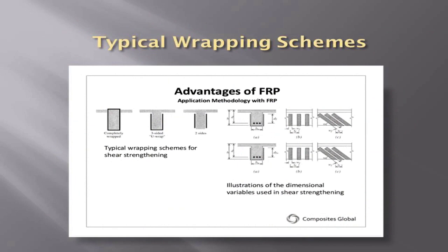Typical wrapping schemes that you see. Here's a schematic for the most common shear wrapping with FRP. Most shear wrapping strips that you'll see are vertical, three-sided U-wraps. This is most common in our inventory. Sometimes you'll see them at diagonals, but usually it's a vertical shear wrap. For flexure strengthening, typically it's a single wrap just on the bottom flange of your girder. The fully wrapped configuration, I'm not aware of any on our inventory, but it's probably the strongest configuration. Three-sided is going to be stronger than two sides.